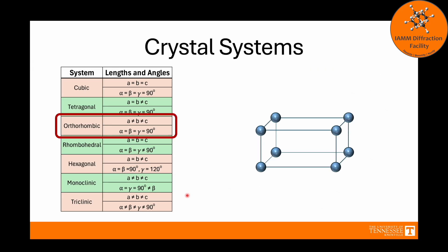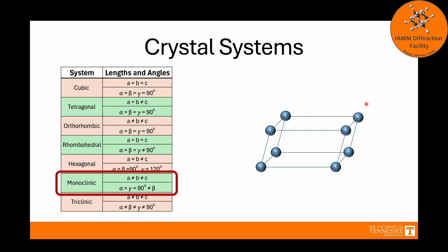Let's go back and grab the orthorhombic unit cell so that we can develop monoclinic from that. With orthorhombic, none of our three edges are of the same length, but all our angles are equal and equal 90 degrees. For monoclinic, again, none of the lengths equal each other, but now two of our angles equal 90 degrees, and the third angle does not equal 90. One way to think about this is, once again, keeping the lengths rigid so that they do not change. Just take, for example, this top plane of atoms and shift it to the right. If we do that, we see that this angle is still 90 degrees, this one still equals 90 degrees, but now this one will be different from 90.